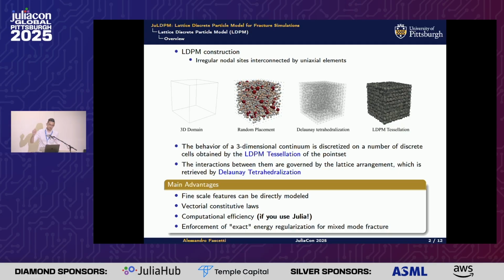Then if you take the centroids of all these particles and you perform a Delaunay triangulation, you obtain a very dense network of 1D elements. All the edges of the tetrahedra that are obtained from the Delaunay provide you with this very dense network of elements. We call these the lattice elements. And so the general idea is that we schematize the three-dimensional behavior of the material, of the continuum, as discrete interactions on these 1D elements. This brings a lot of interesting advantages, particularly because all of your tensorial constitutive relations become vectorial at the 1D level of the lattice struts or elements, as we call them.